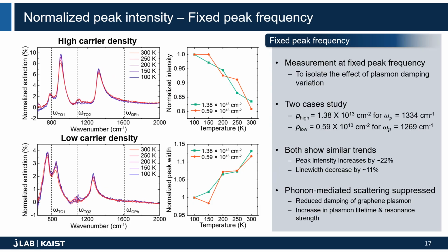Finally, to exclude the effect of cooling-induced additional doping, we carefully equalize the resonance frequency at every temperature. That means we can isolate both the additional doping effect and the plasmon damping variation. Even after excluding the additional p-doping effect, the normalized peak intensity still increases with cooling. Also, the line width of the GP resonance peak, which is inversely proportional to the plasmon relaxation time, is observed to also decrease with cooling.